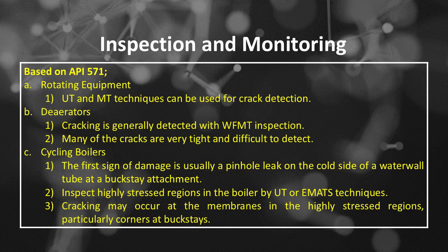Corrosion fatigue damage prevention and mitigation based on API 571. Number A, for rotating equipment, UT and MT techniques can be used for crack detection. Number B, for deaerators, cracking is generally detected with WFMT inspection. Many of the cracks are very tight and difficult to detect. Number C, cycling boilers: the first sign of damage is usually a pinhole leak on the cold side of a waterwall tube at a buckstay attachment. Inspect highly stressed regions in the boiler by UT or EMAT techniques. Cracking may occur at the membranes in the highly stressed regions, particularly corners at buckstays.